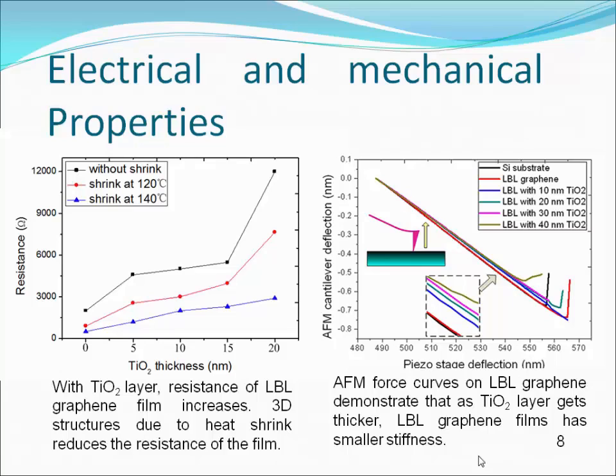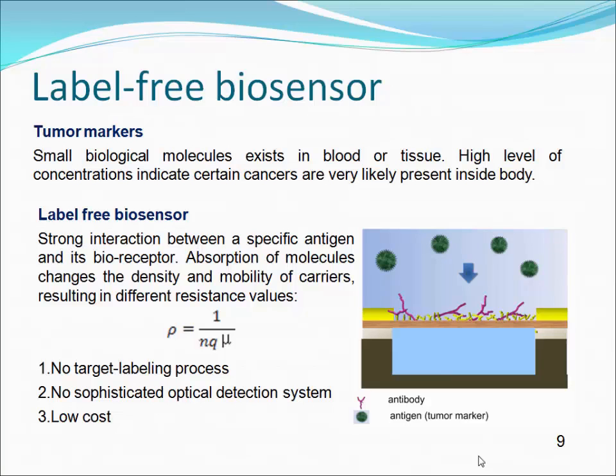mechanical properties. And from this picture, you can see that when the thickness of titanium oxide layer increases, the slope of this retraction force curve of AFM also reduces. So for the layer-by-layer graphene, that indicates the graphene film has smaller stiffness. So the stiffness of these new components can also be changed by adding titanium oxide nanoparticles. And then we further investigate the properties of these new graphene components in the application of biosensing.